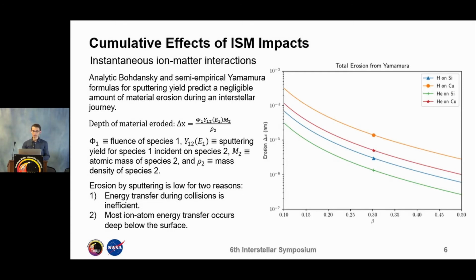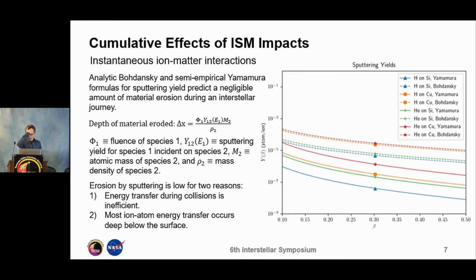And this is the case because energy transfer during collisions between highly energetic light ions and heavy atoms is inefficient, as well as because the energy transfer occurs deep below the surface where the nuclear stopping cross-section becomes comparable to the electronic stopping cross-section. This shows the same thing just for silicon and copper. Sorry, this shows the sputtering yield.